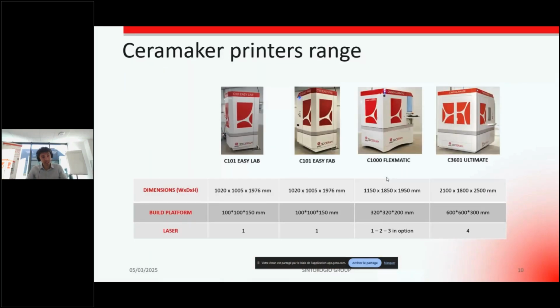As we're speaking about the machine, let me explain in more detail our range of printers. So thanks to SLA and the top-down process, we can offer a wide range of machines with the same process and the same slurry to allow quick and easy scale-up for our customers. We have the small one, the C101 Easy, with one UV laser inside, and a printing platform of 100 by 100 by 150 mm. We have the medium size machine, the C1000 Flexmatic, with a printing platform of 320 by 320 by 200 mm. And this machine can have 1, 2, or even 3 UV lasers in order to decrease the printing time.